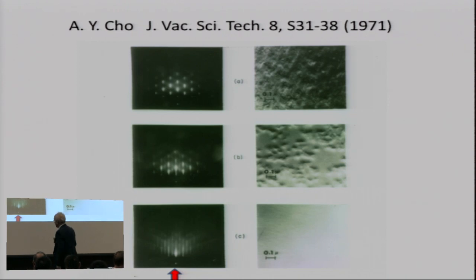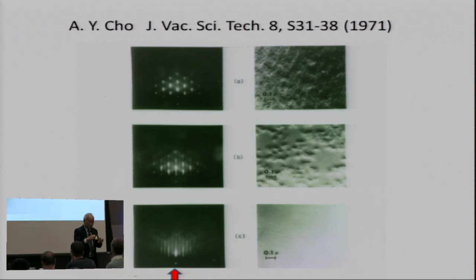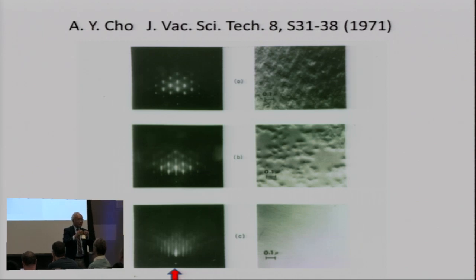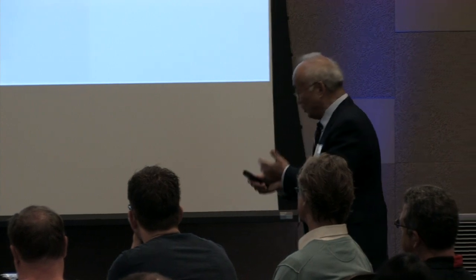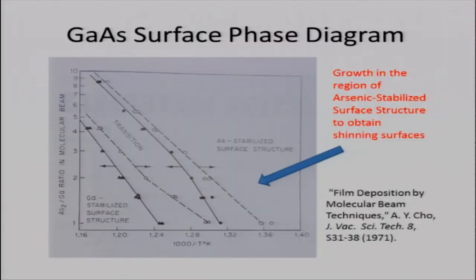Furthermore, when we get so smooth, you see the fractional one-half order showing in the 110 azimuthal direction. That shows the atoms in the 110 azimuthal are two times larger than the bulk crystal in real space. So with that, I found that if you use different arsenic to gallium ratios and different substrate temperatures, I therefore plot the arsenic to gallium ratio on the vertical scale and 1,000 over degrees K on the horizontal scale.